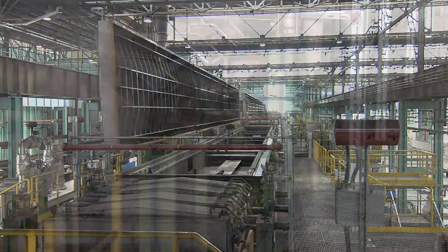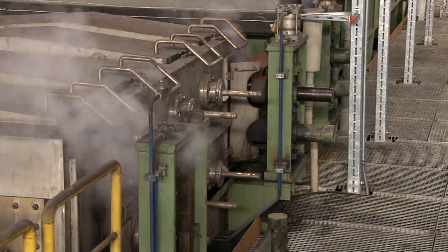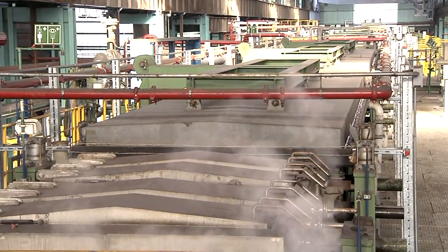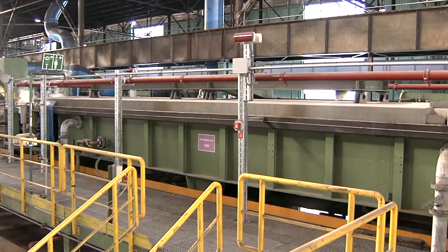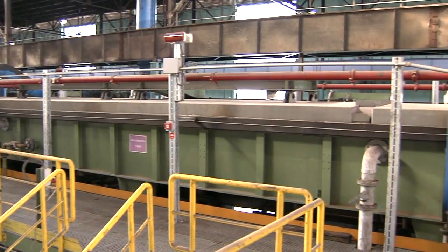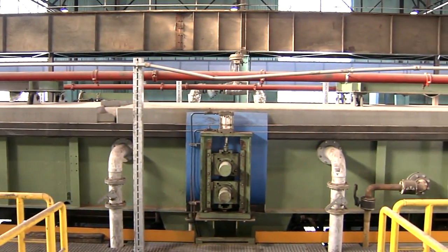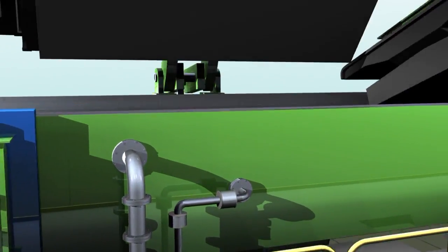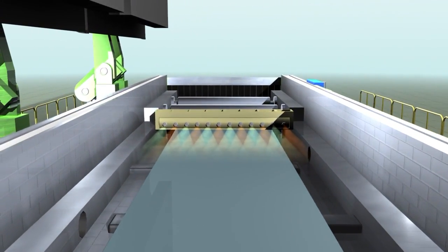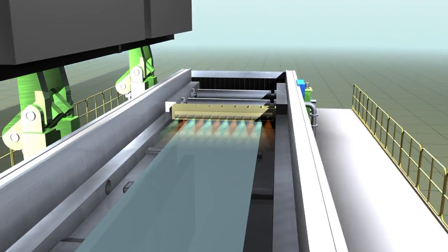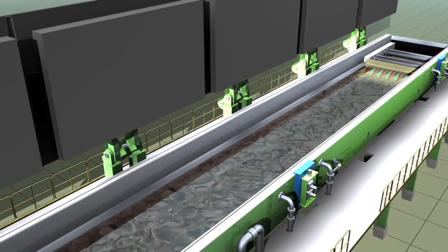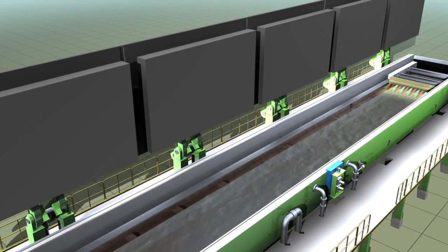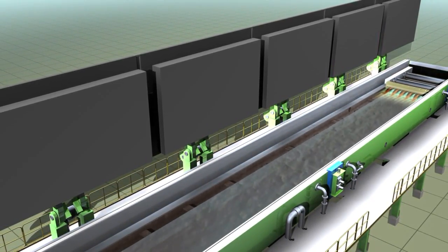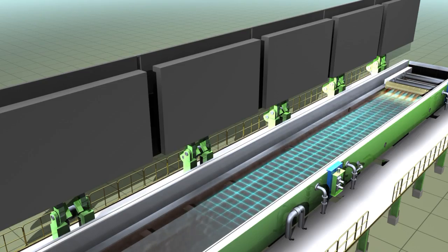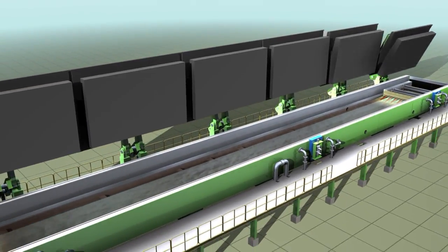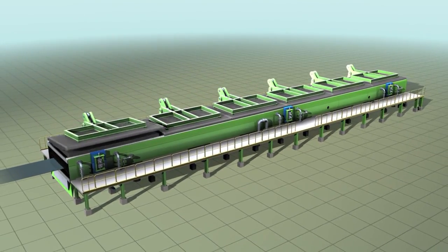First comes the turbulence tank with sulfuric acid. The turbulence process developed by SMS Siemag excels through its high pickling capacity and low operating costs. Here the strip is guided through flat pickling channels containing spraying headers. Strong turbulences arise due to the constant inflow of acid and the low height. The entire strip surface is thus wetted with minimized acid use. Less acid also means less energy consumption for heating.